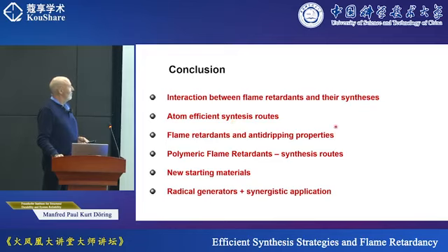This is a very nice and interesting field because of possible banning of Teflon derivatives, the classical anti-dripping agents in polyamides and polyesters. Polymeric flame retardants are going more and more of interest because they have very nice properties regarding the matrix polymer on the one side and less problems on registration.